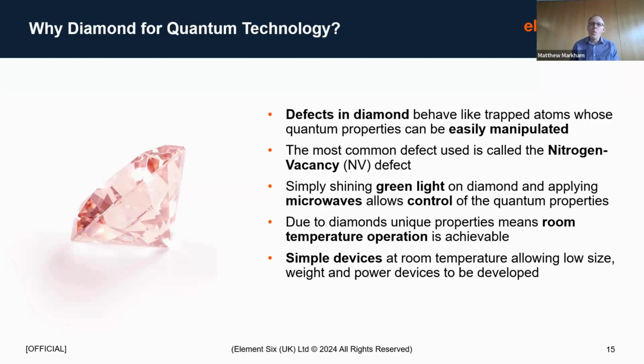And it's this defect which is actually responsible for making synthetic diamonds the pink color, as shown on the left here. Why diamond is such a good material for this is that the diamond crystal lattice doesn't really interact with this spin. So whilst the diamond itself is at room temperature, the temperature associated with the spin is actually of the order of microkelvin. So you've got this good separation between the quantum properties and the host material, which is diamond.